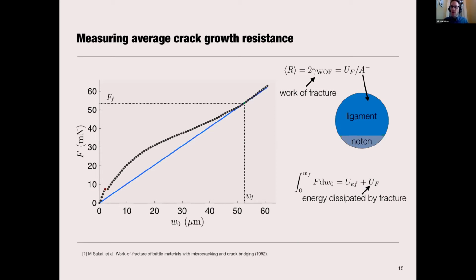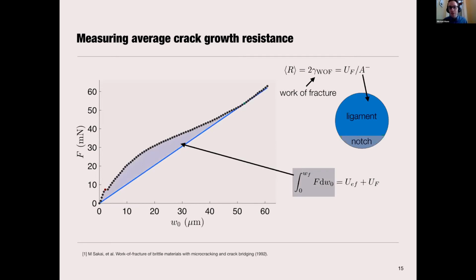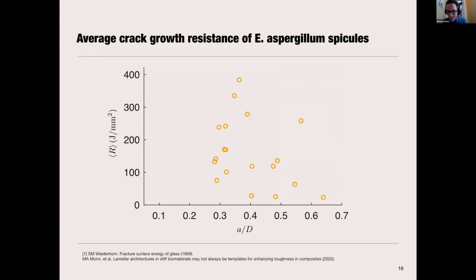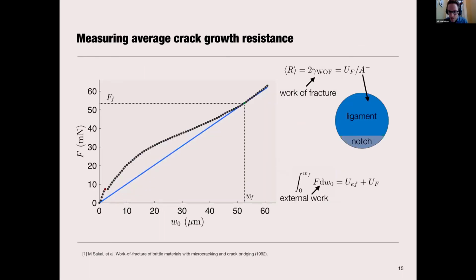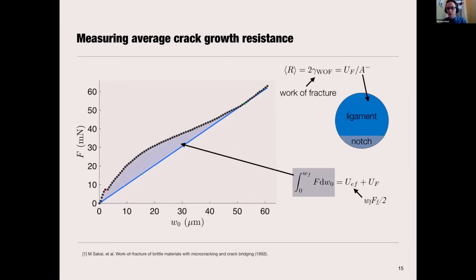For example, for a standard CT test or a standard 3-point bend test. Once the sample has failed, it is no longer carrying any sort of load, so your elastic energy will be 0. In our case, that's not the case because of the cantilevers that I showed you previously when the sample is in its completely failed state. So the left-hand side, the external work done, can be found by the area in between the loading and unloading curves, or more cleanly in this case, the area between the loading curve and that line of minimum elastic compliance drawn to that green dot, that point of failure. And the elastic energy is force times the displacement divided by 2.